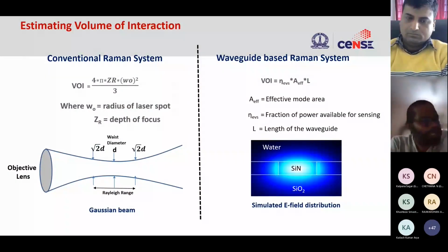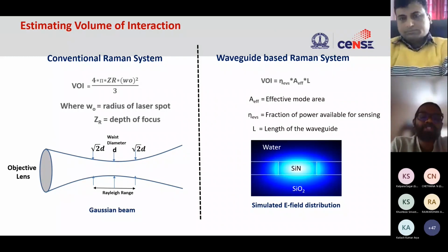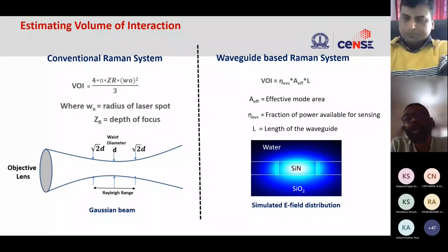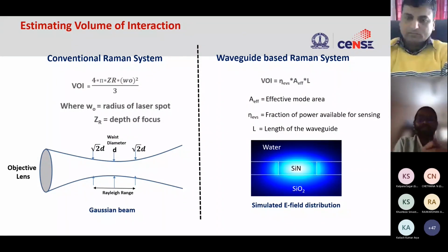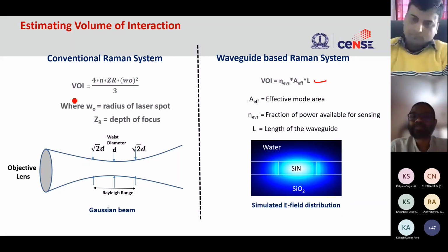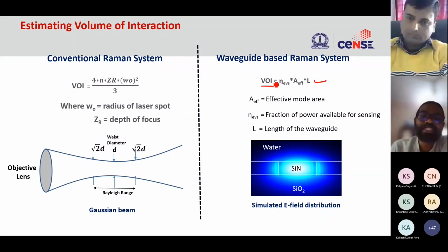For some of you wondering why the waveguide system is better than a conventional Raman, here is the slide to convince you. Conventional Raman depends on your focusing capacity, right? You have to focus to a tighter spot in order to get this signal out, because the efficiency of Raman is very low. However, in a waveguide geometry, your waveguides can be made centimeter or millimeter long. So the interaction length gives you this volume of interaction. You can increase the volume of interaction by increasing the length. In the conventional case, you have to make sure your laser spot is tight.